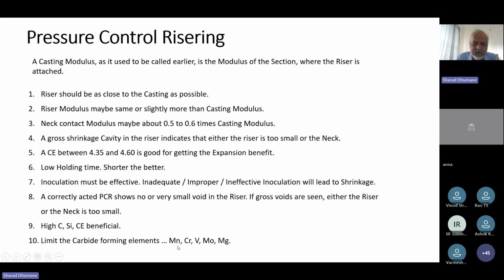Limit the carbide forming elements. Okay, this is just a theoretical statement. Sometimes we have to pour with this element, this chemistry, and then we have to take suitable action. But yes, as far as possible, for example chromium. You can avoid or reduce the chromium amount by suitably deciding your carbon equivalent. If you decide your carbon equivalent on the lower side, up to 260 grade in gray cast iron, you don't need copper or chromium. So you can make FG260 grade with all tensile and hardness requirements. You can fully comply with those with low amounts of carbon and low amounts of chromium. So as far as possible, you can avoid these carbide forming elements by selectively choosing your carbon equivalent.